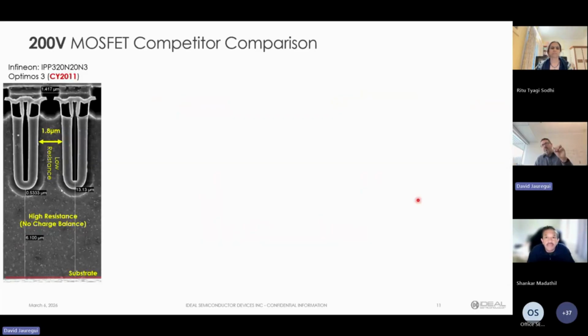So, building on that 200-volt MOSFET structure, this is that structure that I talked about that is now different than the classical superjunction that I showed at the onset. This still relies on charge compensation or RESURF to try to deplete the drift region, but it does it with a capacitively coupled field plate. So this is actually metal, and this is an oxide. What it does is capacitively couple the drift region, deplete it, and block. And so all the current has to flow through this region, and then they add this lower doped, higher resistance buffer layer to help improve the blocking voltage.